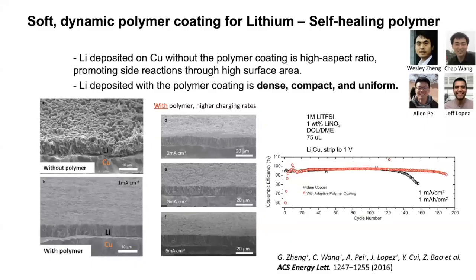I won't go into too much detail. Without this polymer coating, dendrites form. You can see all these chunky column-like lithium. And then with the coating, we completely change the way lithium grows. It becomes very dense and very smooth. So this allowed us to make lithium metal much more stable compared to previously possible.